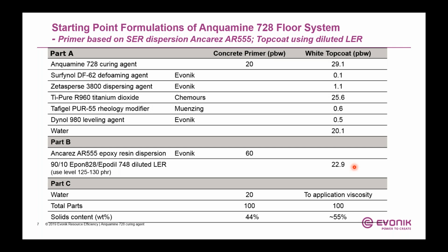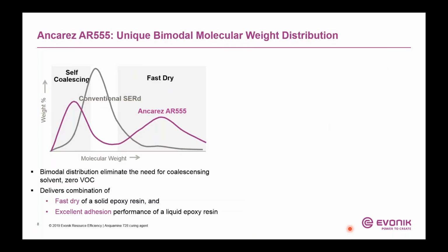So why are we using liquid epoxy resin? It will not only meet the speed requirement, but most importantly, using liquid epoxy resin will cut down the cost for your entire floor system and will still meet one-day flooring. If we look at the primer formulation, the primer is a clear coat, just resin and curing agent with water at about 45% solid, and the top coat is a glossy white top coat at 55% solid.